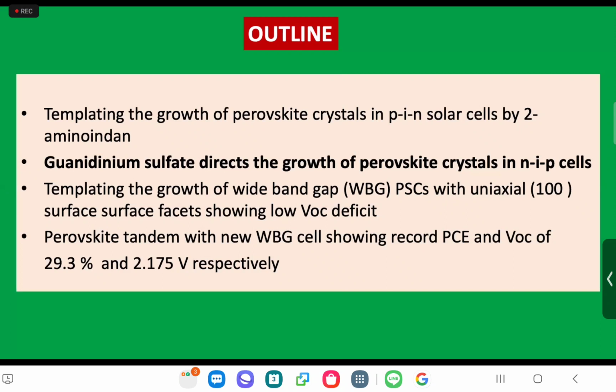also reports on directed growth, this time on an NIP structure. And so the NIP structure is such that when you put the perovskite down, it will see the electron selective contact first. And these are nanocrystals, quantum dots of tin oxide. That's our electron selective contact. However, this contact can be improved. And so here it is shown that by just treating the tin oxide quantum dots with guanidinium sulfate, you